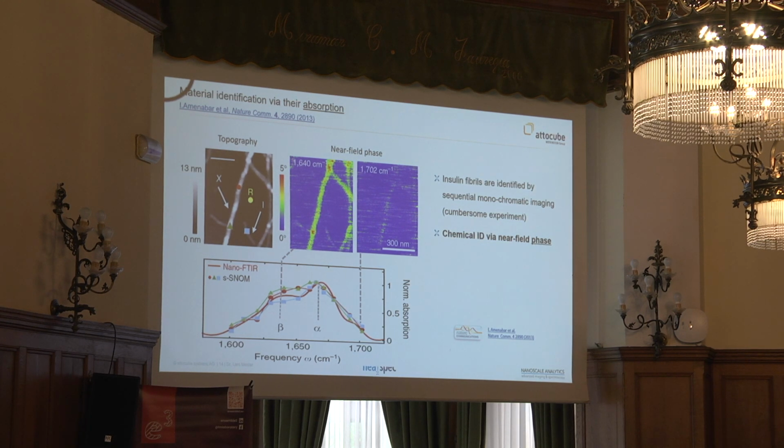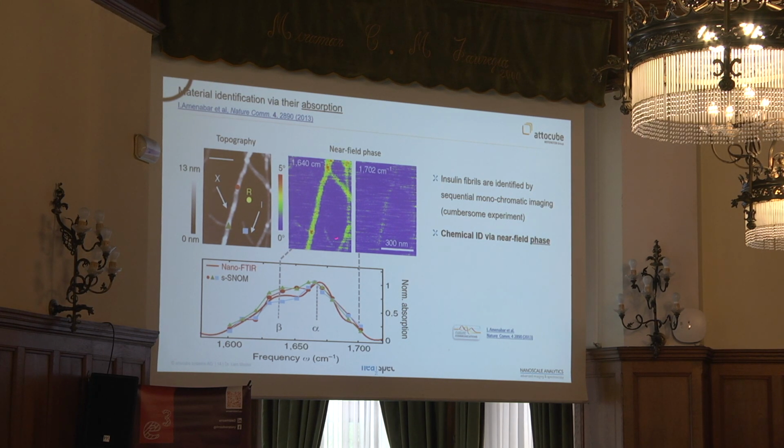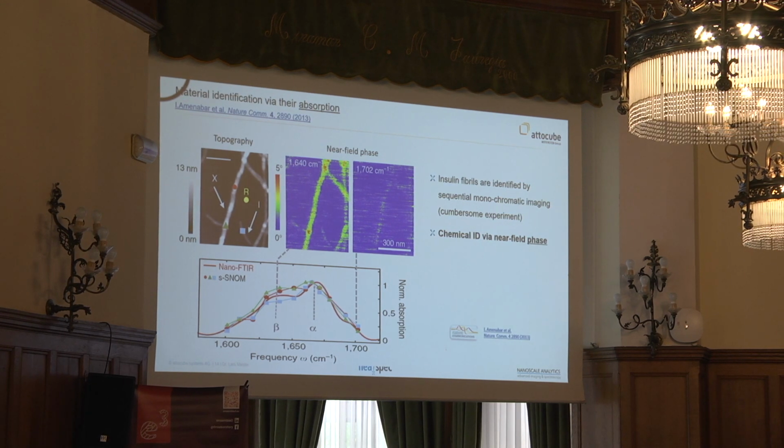And this was one point that was already shown a few times, but not explicitly mentioned: you can take a spectrum also with a series of images. So you don't take 2 images, but you take 10, like shown here. And you can map the spectrum. It's a very tedious experiment, but before there was a nano-FTIR laser, that's what you had to do. And the nice thing is, if you now have the nano-FTIR laser, it's much easier. Of course, you get only 1 pixel,